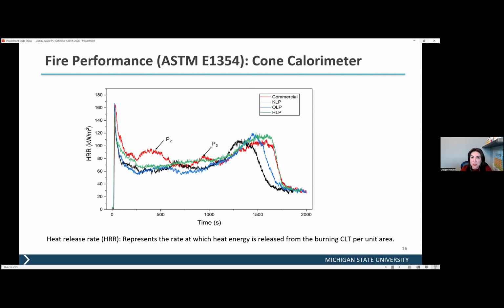We collaborated with Forest Products Lab. Our colleague, Laura Hasburgh, did this fire performance test for us at Forest Products Lab. This is based on ASTM E1354 cone calorimeter test, where the samples are basically put into cone calorimeters. We tested again three lignin-based adhesives and the commercial adhesives.